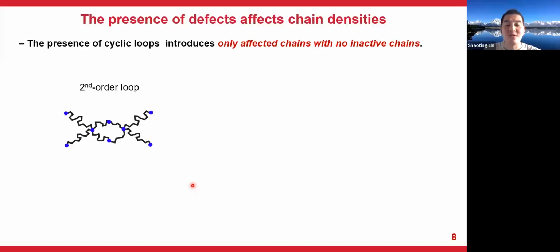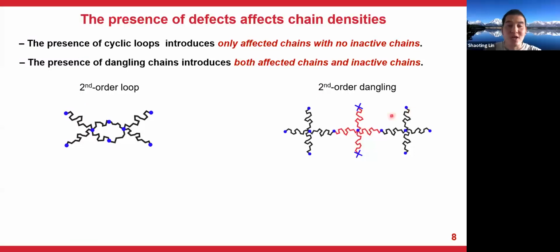We further quantify the number densities of different types of chains due to the presence of defects. The presence of second order loops, first of all, does not introduce any inactive chains. But secondly, it will introduce affected polymer chains. What's different is that for the dangling chains, it will introduce both inactive chains and affected chains. So here's one example. The presence of one second order loop actually makes the one original chain become longer, but does not introduce additional new active chains. Alternatively, in other words, all the arms of this polymer are inactive in some sense.